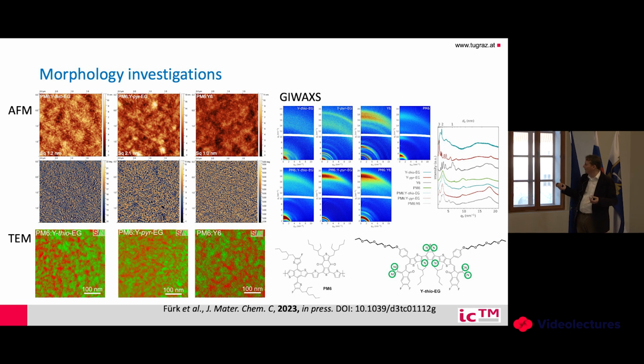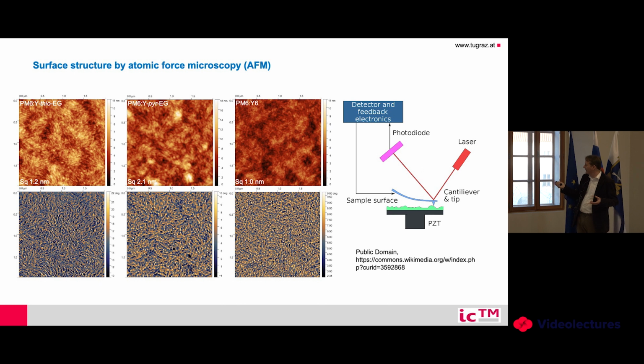So actually you image the topology. It's like a relief structure of your surface, by having a tip, which is not scratching your surface. This tip scans your surface, and you have a deviation which can be measured very accurately with a laser. So the exact position of your tip is monitored by a laser, and this is the morphology. Then you have here the surface image of your material. There are different modes. Usually you don't have direct contact, but you can also have direct contact, and you can also have an amplitude mode.